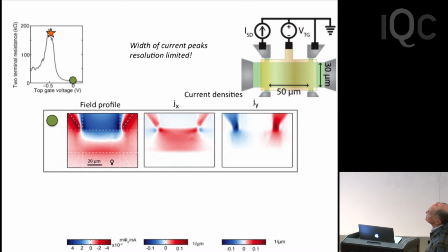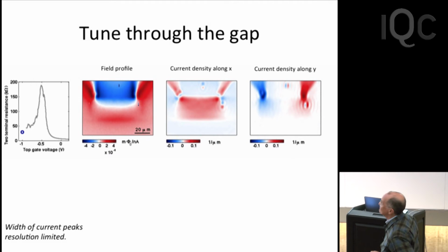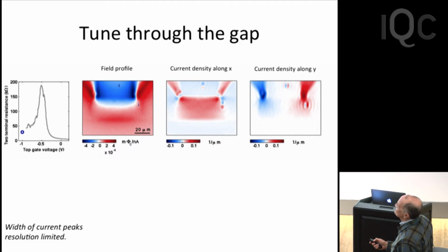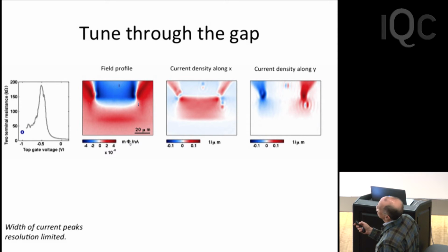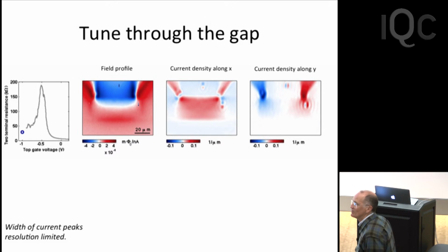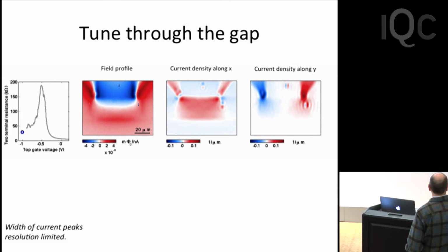You can also tune the Fermi level through the gap and make a little movie. So this little dot shows you the resistance of the sample. So right now I'm freezing out the bulk, and now you're getting both bulk and surface. And you can see that one thing that should be pointed out is that there's both bulk and surface conductivity happening at the same time, say right there. And also, of course, the imaging shows you about inhomogeneities, which bulk measurements don't do.